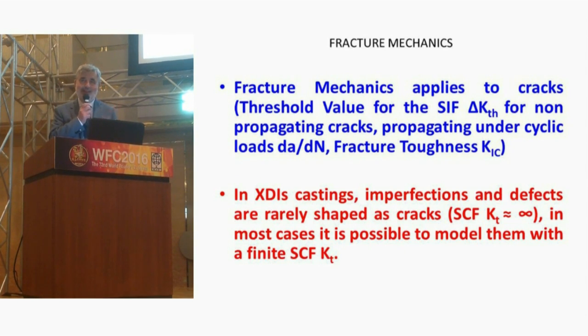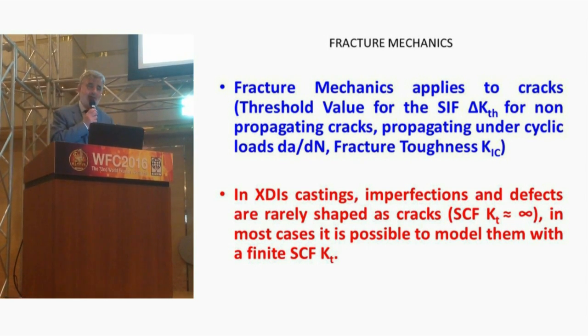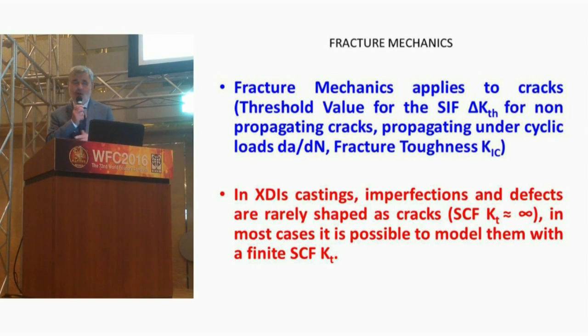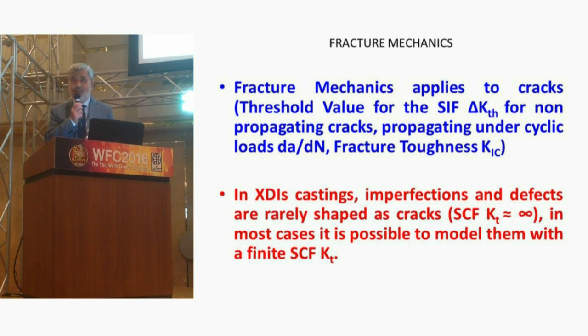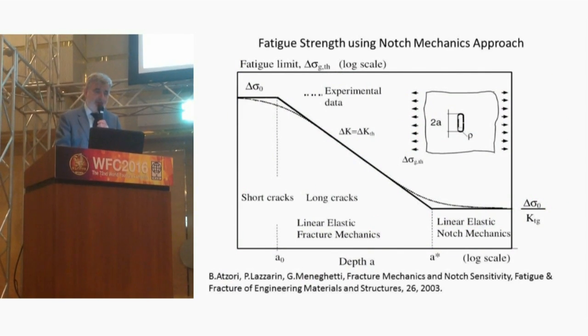In XDIs casting, I always use XDI to mean every kind of ductile iron: normal, pearlitic, ferritic, silicon, or austempered. Imperfections and defects are rarely shaped as cracks, as happens in steel, for instance. And so the stress concentration factor, KT, could be not infinite, could be at a limit, could be calculated or assumed. And so this is very important.